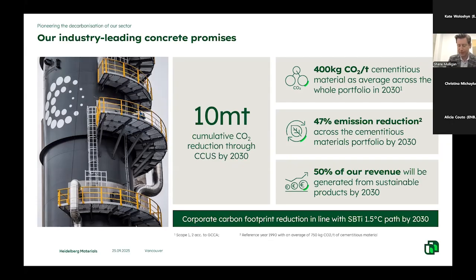And for context, the carbon intensity of our best plant in North America is located in Delta, British Columbia, just outside of Vancouver. And that has an EPD that says 679 kilograms of CO2 per ton of Portland limestone cement out of that facility. So quite a ways to go to that goal of 400 kilograms. That's a global target, so that averages out what we're doing in Europe and other areas of our operation, but nonetheless is a very ambitious target for us to reach.